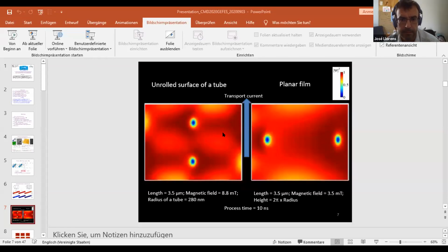Yes. Okay, in the left-hand panel, we see here a surface of a cylinder where one vortex, the upper vortex, flows from the right to the left and the lower vortex from the left to the right. In the right-hand panel, we see a normal, typical situation for a planar film where vortices flow one after another, and you see now a video. They go in one direction. The motion of vortices in the upper and lower halves is correlated, and this is a direct consequence of the complicated topology of screening currents.